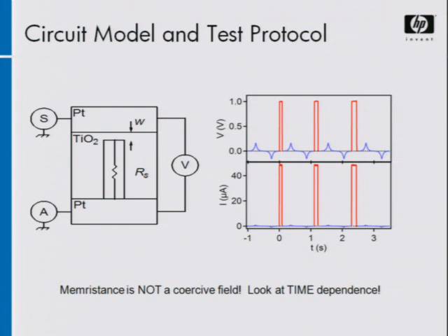All right, then we test the device as a function of time for a different bias voltage. Then we have to reset the device back again to its initial state, test it for another voltage, and we have to do that for several voltages in order to be able to look at both, essentially, the time dependence, which will give us flux or charge dependence, and because these are nonlinear devices, we also need to look at the explicit voltage dependence of what's going on.